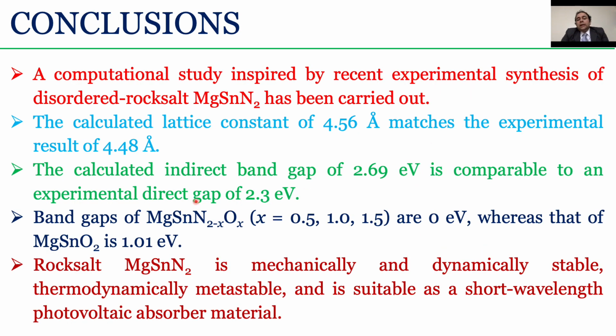Finally, we can conclude that the calculated lattice constant and band gap for disordered rocksalt crystal structure closely match the experimental result. Magnesium tin nitride in disordered rocksalt crystal structure can be utilized as an absorber layer in the higher energy range of the visible range, whereas the other two crystal structures can be used as window layers in solar cells.